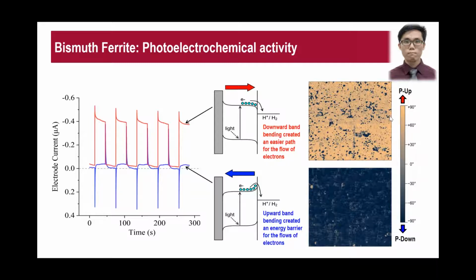So we can have a better understanding by showing here that P up will lead to a downward band bending, and this downward band bending will create an easier path for the flow of electrons, whereas P down will generate an upward band bending. And this upward band bending will require a higher potential barrier for the electrons to overcome. This can be proven from the electrode current that we have measured here, indicating that indeed there is downward band bending and upward band bending that control the flow of electrons. And all of this is actually affected by the polarization directions.